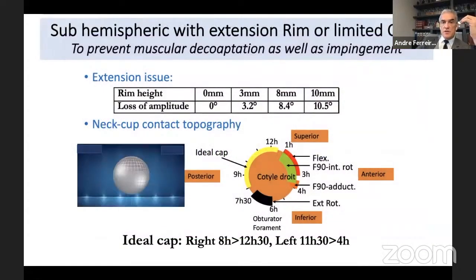And a subhemispheric design with an external rim can be used, and we can see that we can limit this rim, like in the schema you can see now. This rim, the extension rim, can be placed only in the location where dislocation can occur, and then we have no rim in the other parts of the shell to avoid any conflict with the psoas tendon, for example, or at the posterior part with the neck and with a risk of dislocation.